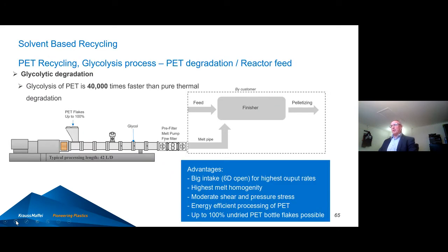This is the typical glycolysis process for PET. So we melt a PET with an IV of 0.65 to 0.7. We add the glycol. We bring this IV down to 0.2 to 0.4. And that melt stream is fed via a pump into the finisher, into the reactor again in the second step, and being part of 20-25% of the mainstream, being processed as a real used material again. Okay, next slide, please.